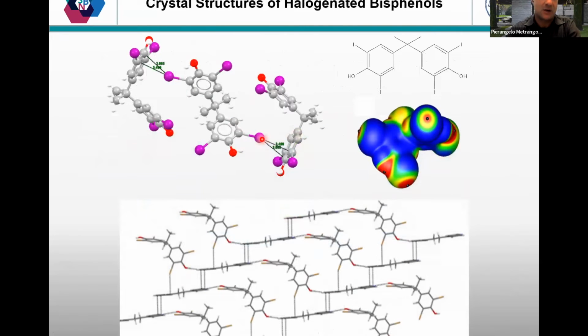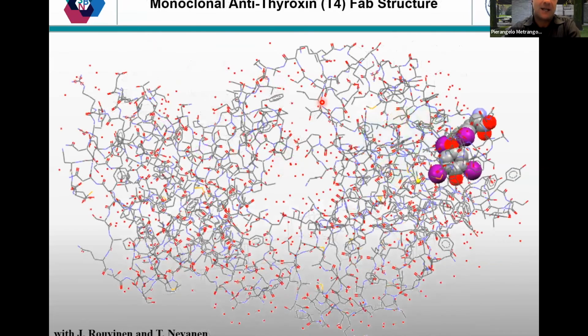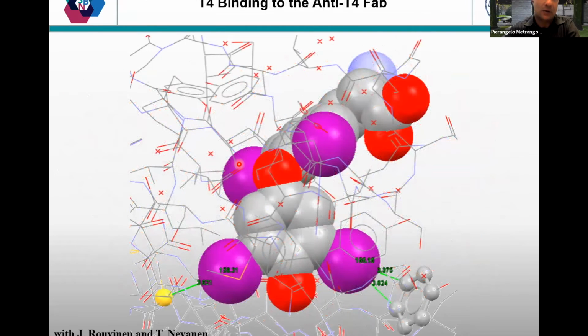We reported the single crystal structure where you can see that the sigma hole of the iodine is looking for electron density on the tyrosine ring. And finally, we were able to crystallize a single crystal structure of a recombinant antibody binding thyroxine. And as you can see, thyroxine is bound to the antibody thanks to halogen bonds, sulfur to iodine, and the same iodine-tyrosine interaction that we saw in the homocrystal.